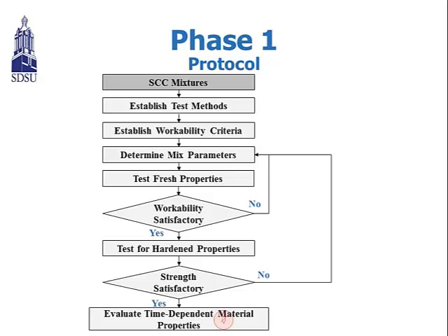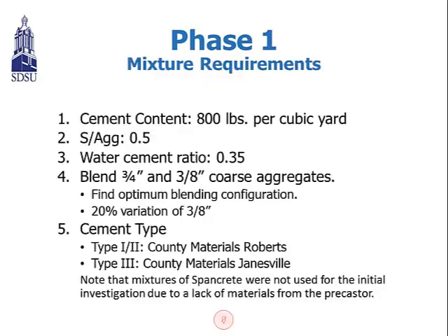And also we determine the mixture parameters, what percentage sand aggregate ratio and the water cement ratio. And then we test for the fresh properties, and then we analyze the data, and then we get the promising or satisfactory mixture that meets the workability requirements. We go on to test the hardening properties, which is the compressive strength test at 18 hours and 28 days. And then we see whether the strength is satisfactory. We move to the evaluation of time-dependent material properties testing. And this is the criteria to check the satisfaction of the mixtures.